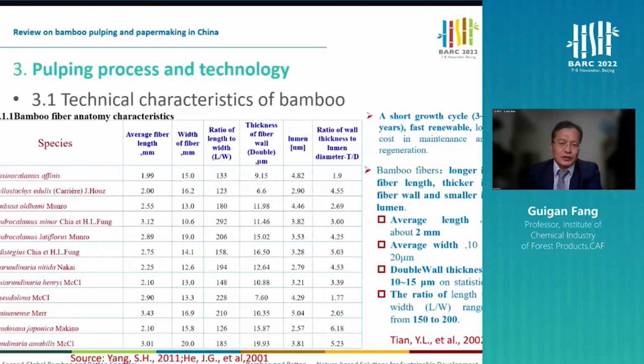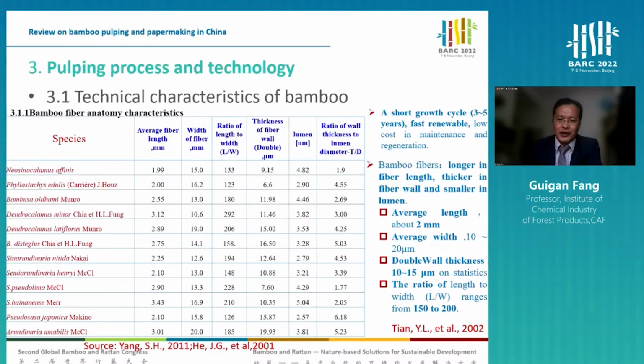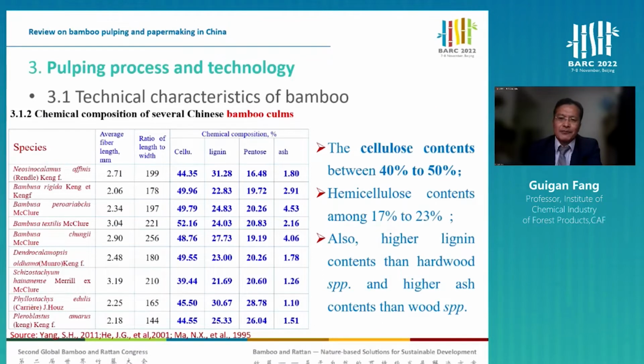Now let's touch upon the pulping process and technology. As we know, chemical, mechanical and semi-chemical methods can be used. First, we need to understand the structure of the fiber. Bamboo is a material high in fiber length. Its average length is about 2 millimeters, the average width is 10 to 20 micrometers, and the wall is only 10 to 15 micrometers. The very good length and width ratio makes it a very good material.